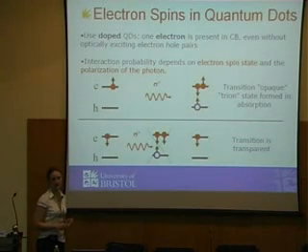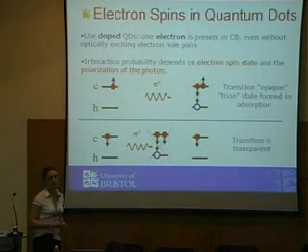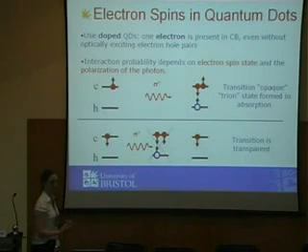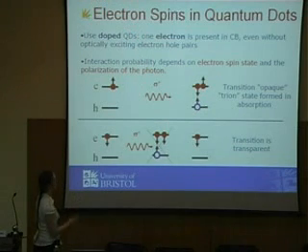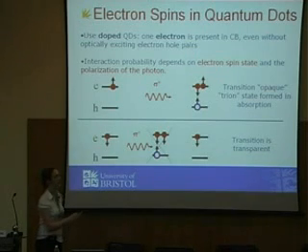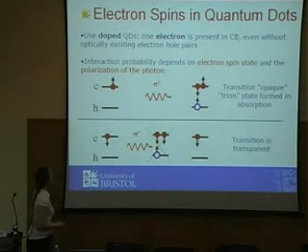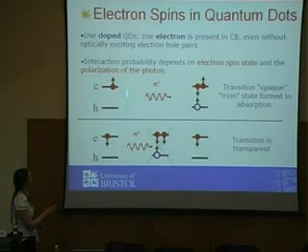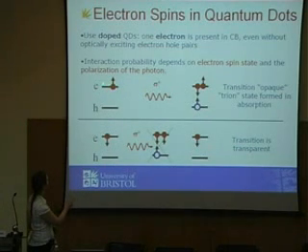And in fact, we use a single electron spin. Physically, what we do here is incorporate the spin by putting the electron into the quantum dot permanently. Practically we do that by doping the quantum dots with a layer of dopant material 20 nanometers below the quantum dots, and then we expect that a single electron occupies each of these quantum dots. Now, the electron obviously has a spin, and when it's inside the quantum dot, it'll be orientated either up or down. Here I'm showing the conduction band and the valence band. This is the hole level, and this is the electron level.